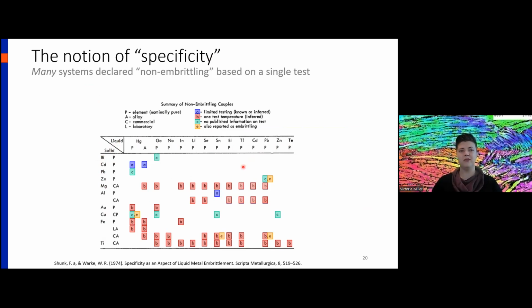The problem, though, is that anything shown in blue has very limited testing. Anything shown in red was only tested at a single temperature. Anything shown in green, they reported it as being non-embrittling, but they didn't report any information on how the test was conducted. And then anything shown in orange has also been reported later as an embrittling system.